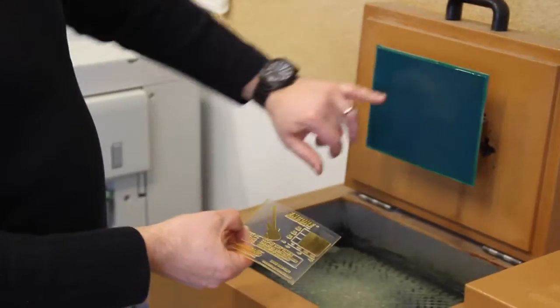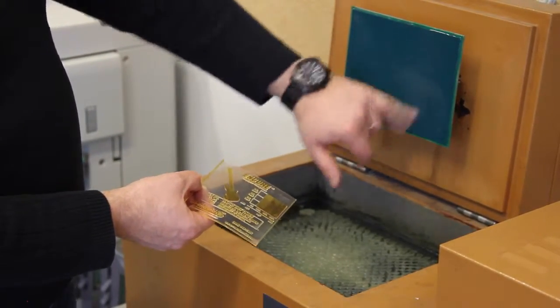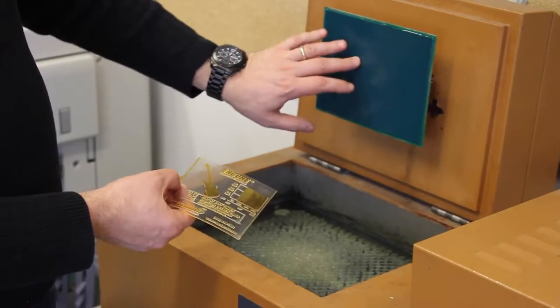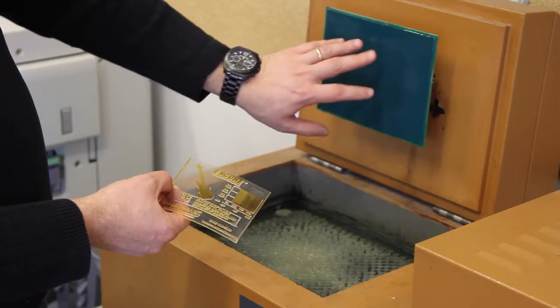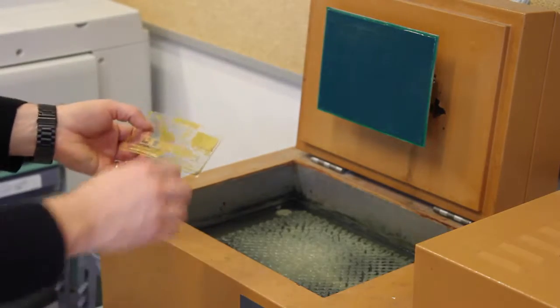One thing I didn't mention about this green material is it's not sticky when it's wet but it's sticky when it's dry. So it's important that when you're done with the wash process that you leave the lid open so that this stays dry and it stays sticky. If it rests in the water it'll begin to deteriorate and we'll have to replace it sooner than we have to.